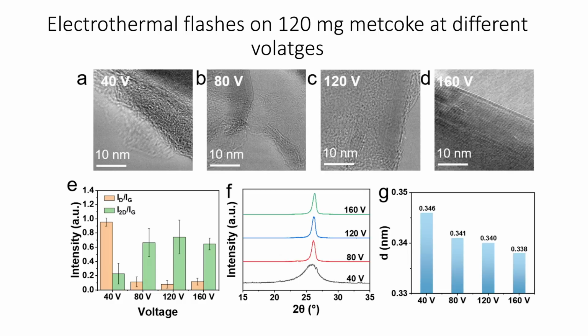You can see the same sort of thing at 40 volts. It's amorphous. At 80 volts, you start seeing the graphitic layers here, the graphene layers. At 120 volts, it starts forming much better. At 160 volts, you've got graphite. You see the nice ordering of the graphite, and the distance between the stacks tracks with this, and so does the X-ray diffraction. So you can see that this is really a process where by energy content you can control the type of material that you're going to get.